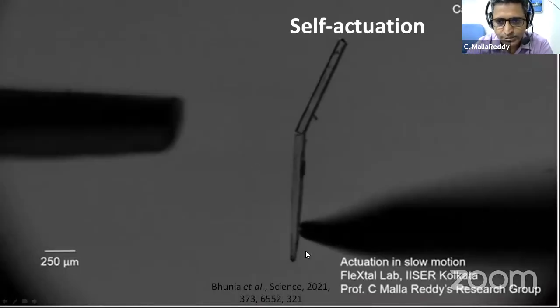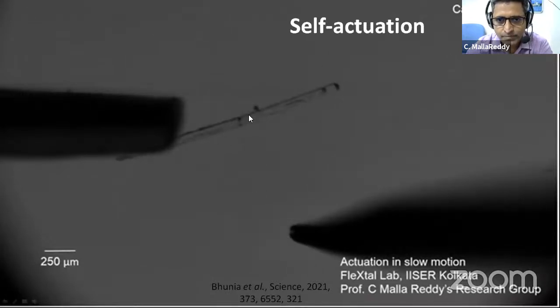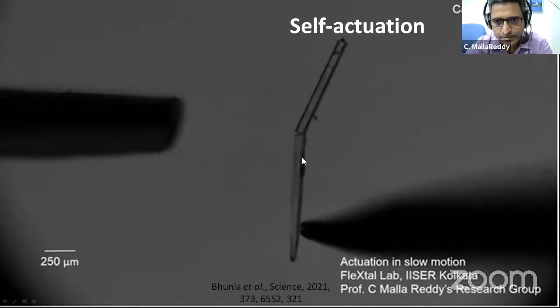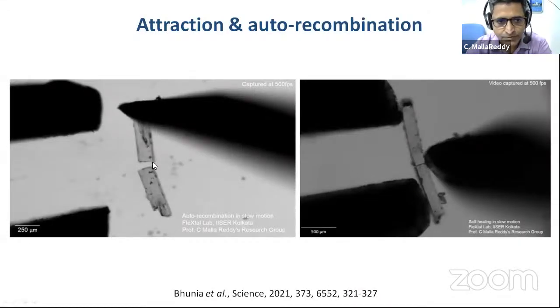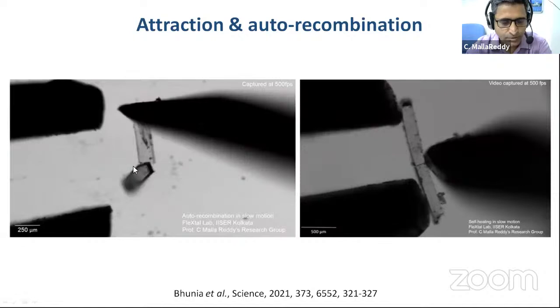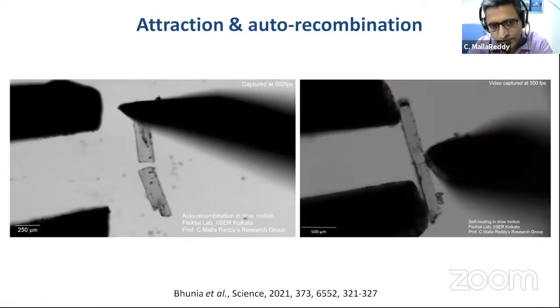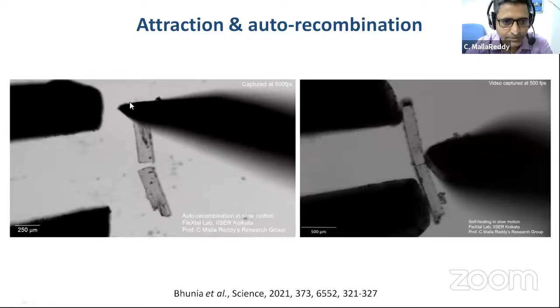Again, you can see here, you just push a cracked crystal, and this whole thing jumps, and there is a lot of motion here. That is because it appeared to us that there is an attraction. Then we got curious, and we wanted to see if you push these particles, once you break them, and bring them closer, whether they attract. As you can see here, this is again a slow motion video. This piece jumps onto it. Okay, so this was about 50 microns distance. So the attraction is at a long range. 50 microns is quite a lot for the kind of attraction that you see here between crystals.